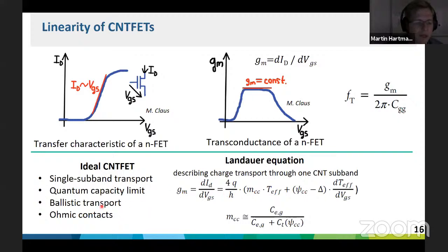And what does this mean? If you have ballistic transport and ohmic contacts, you don't have any losses within the tube. That means that your transmission factor T becomes 1. That means that this derivative vanishes.